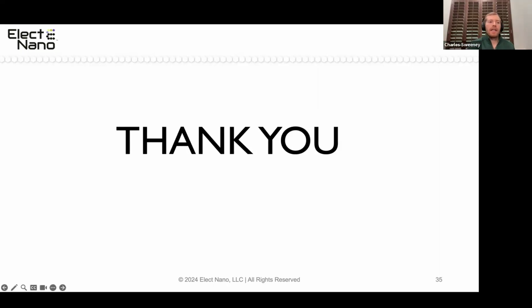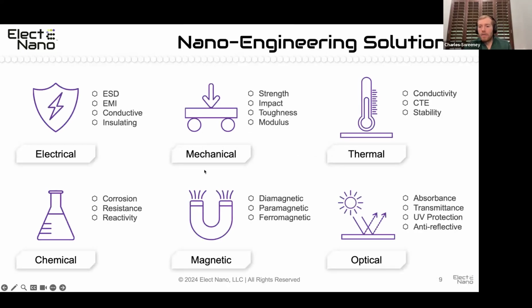Yeah, and it really depends on the final applications. You're exactly right that what and how much you do to the sidewall of the tubes can affect finished properties. For instance, in EMI applications, our goal is to maintain as much of the intrinsic conductivity of the tube as possible. There's also some cool things that our company has figured out in terms of covalent or non-covalent bonding that actually helps to promote percolation. When two nanotubes are near each other, there's a tunneling junction resistance between the two. And there's some situations where you can link those up intentionally in order to promote lower junction resistance. So modifying the sidewall of the tubes doesn't always decrease electrical properties.